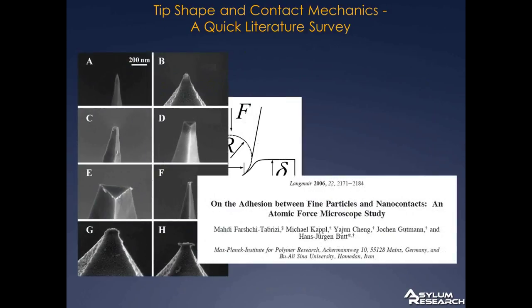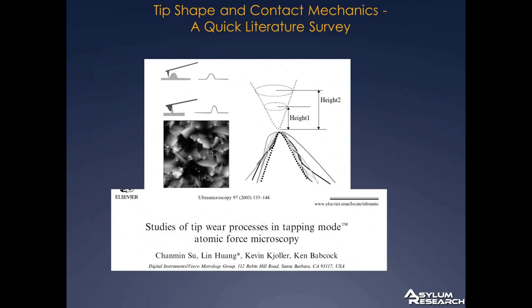Here's another series of shots from the same group where they're looking at tip wear. In this series of shots, the size of the tip, the contact radius, if you can even define one, ranges over several orders of magnitude, and the tip shapes are very complicated and change from tip to tip. Maybe the most disturbing thing is that tips change as we're scanning. AFM is a mechanical process, and so sometimes the tips wear. They may also pick up debris and so on that change their interaction shape.